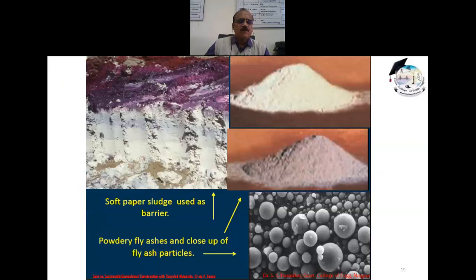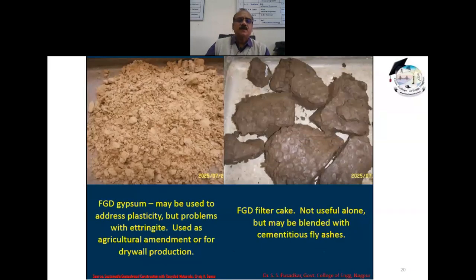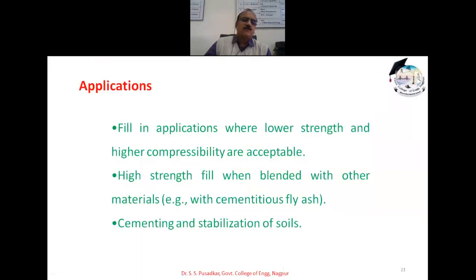It shows some soft paper sludge or the ash contents, with the microstructure of the ash also shown there. You can use these FGD gypsums which I discussed earlier. It addresses the problem of plasticity, but the problem is that we use it as an agriculture amendment or for drywall production. So mostly it is used for drywall construction. The FGD filter cake can be blended with the cementitious fly ash, and you can make aggregate using those materials also. So we can use these recycled fine aggregate materials as fill in applications where lower strength and higher compressibility are acceptable, as high strength fill when blended with other materials, and for cementing and stabilization of the soils.